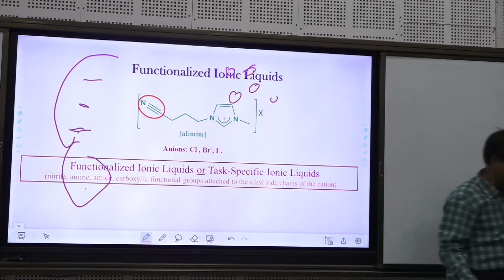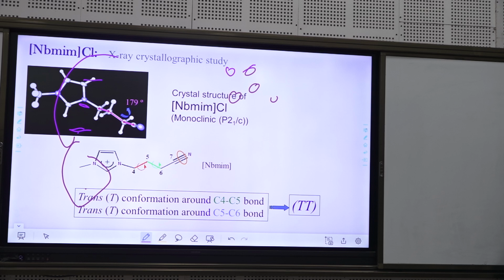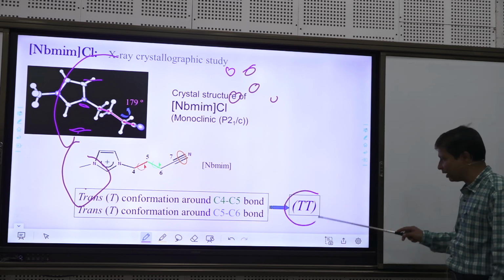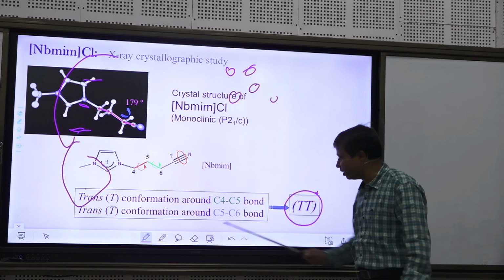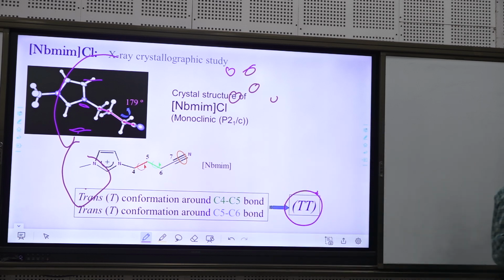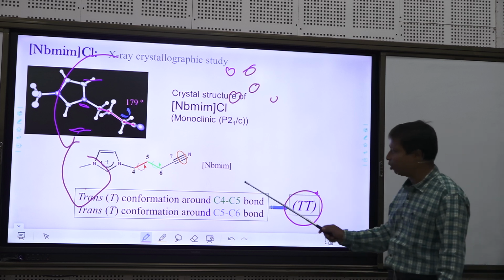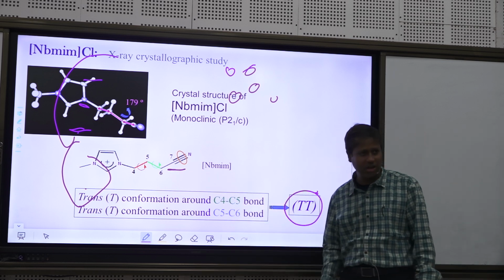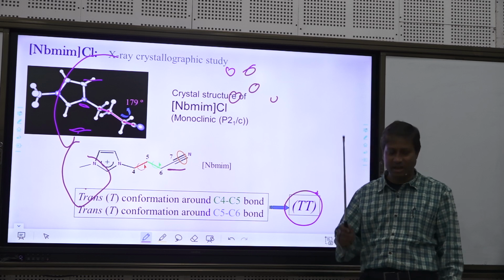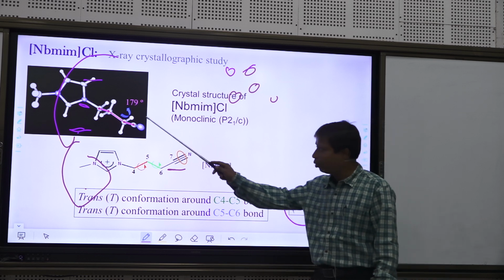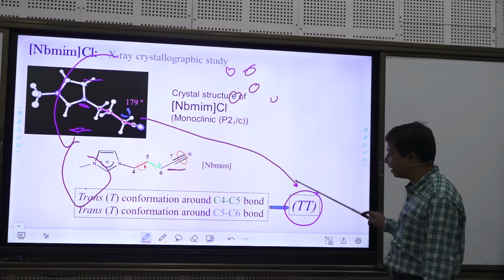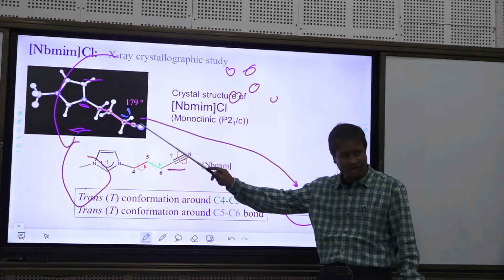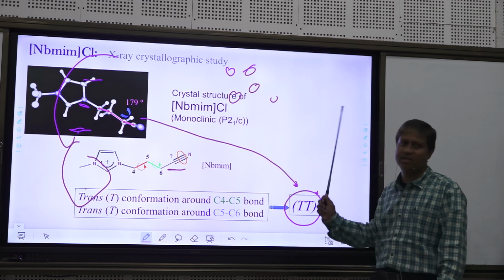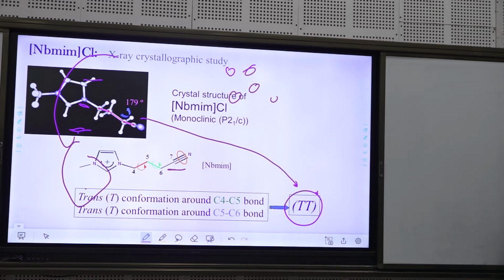Now we have studied this one, which is also known as a functional ionic liquid, and we have done an X-ray crystallographic study. Whatever we have concluded from the Raman data, we found that the X-ray data is also confirming. If we say that this molecule stays in a trans-trans conformation through Raman spectroscopic studies, that is correct, because we crystallized this one and did the X-ray crystallographic studies. The X-ray studies say yes, it is trans-trans. So the Raman spectroscopic conclusion is correct.